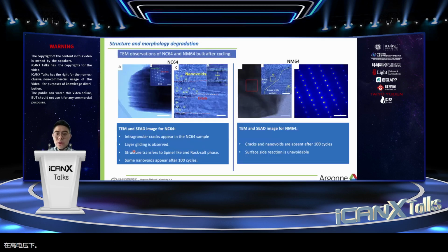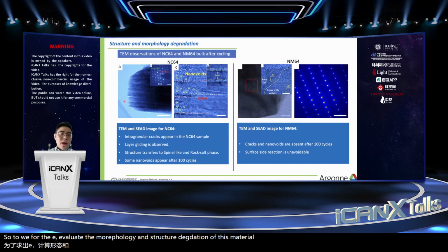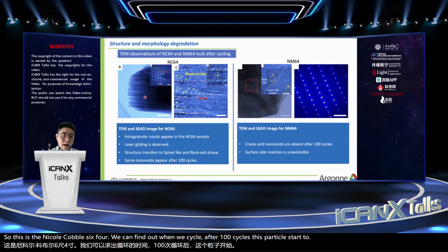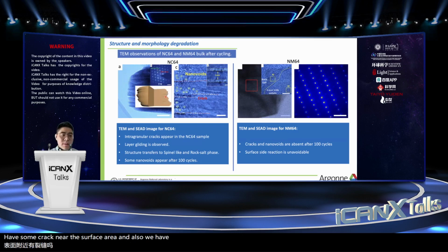So we further evaluate the morphology and the structure degradation of these materials. So this is the nickel cobalt 64. We can find out when we cycle after 100 cycles, these particles start to have some cracks near the surface area, and also we have some layer gliding. That is mainly caused by the huge lattice parameter changes.